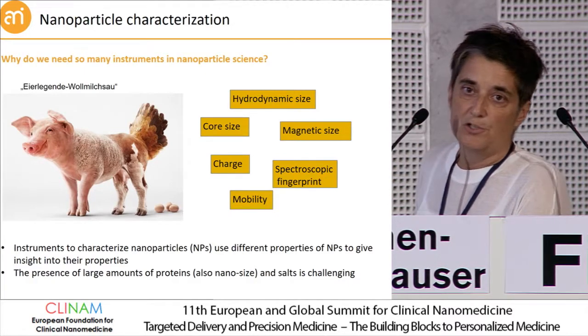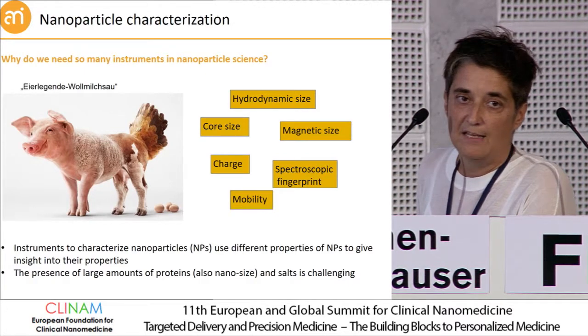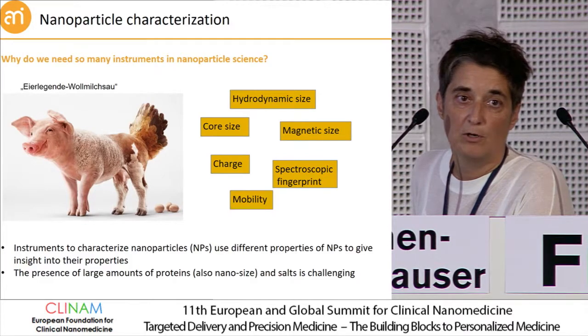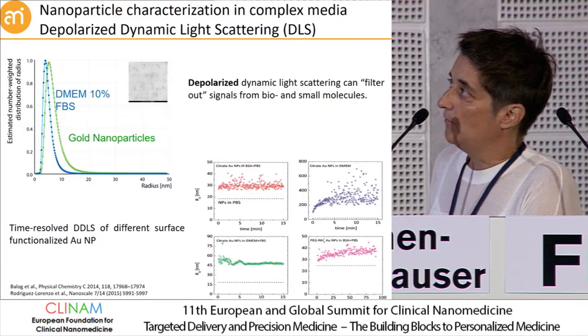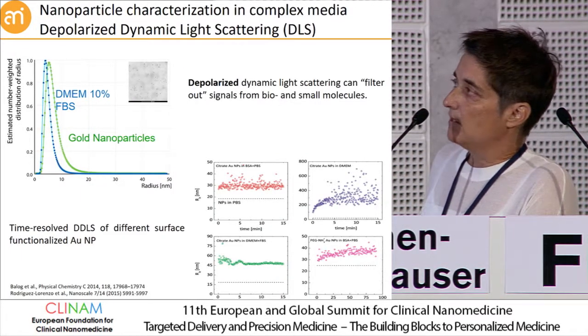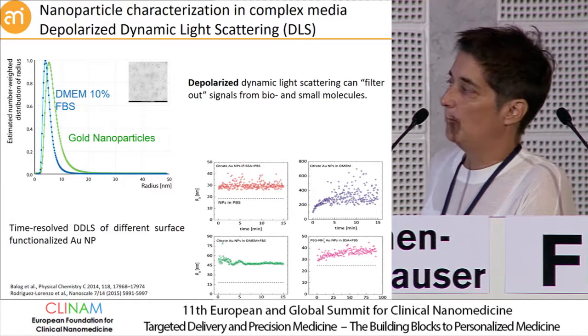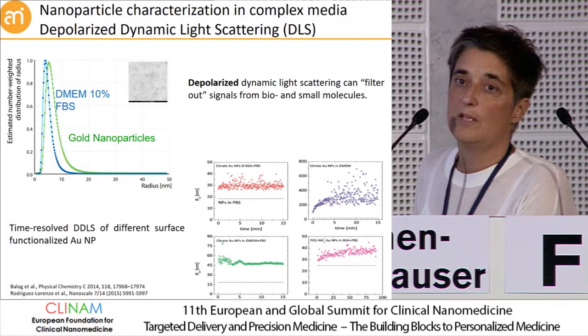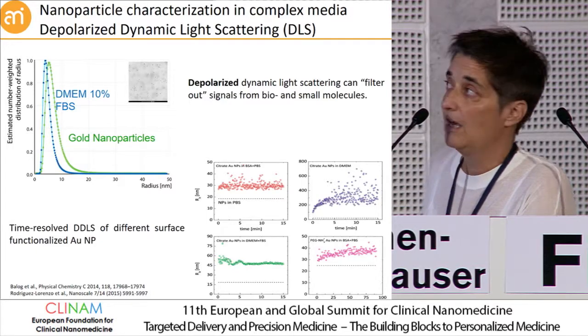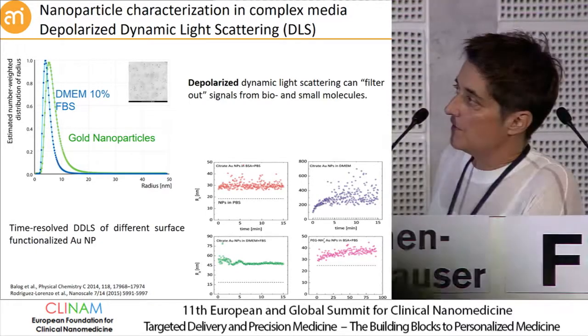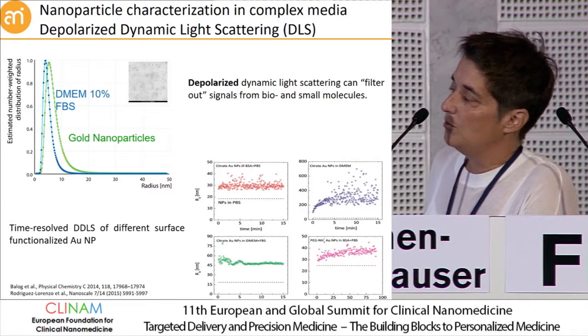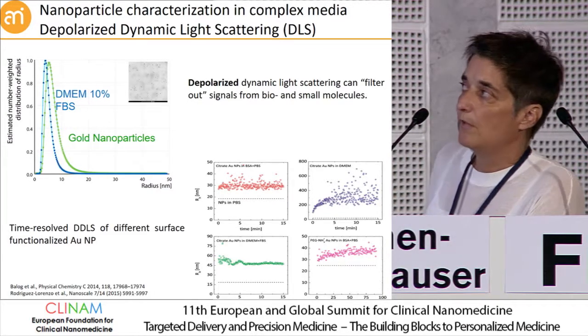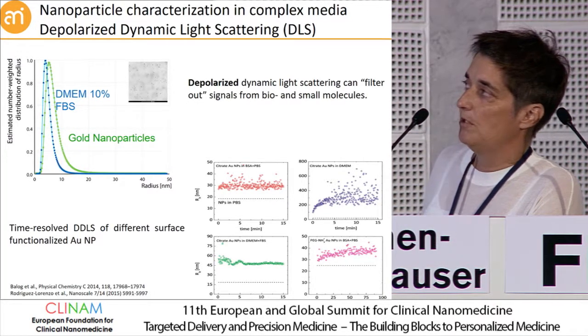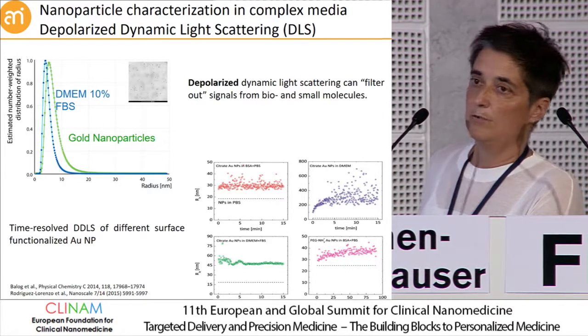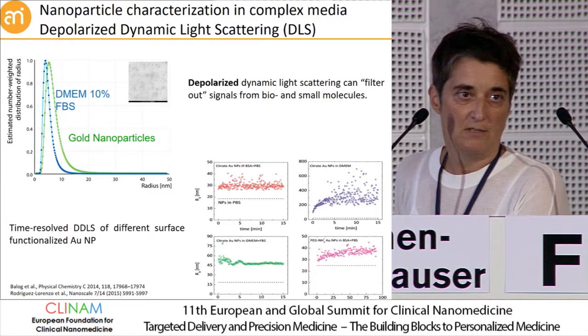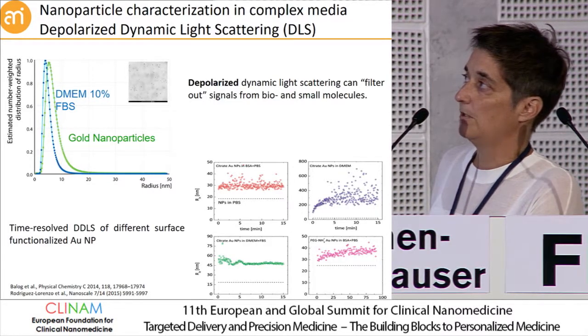Because you have this large amount of proteins, and these proteins end up having pretty much the same size as the particles, and this can be pretty confusing. This is something we did very recently. We used a standard DLS instrument, something that many of us have sitting in their labs. We measured gold particles, this is the green distribution, but we also measured without any particles, just a cell culture medium with a serum, and I think we can agree that this can be pretty misleading, right? Because all you're measuring here is proteins.